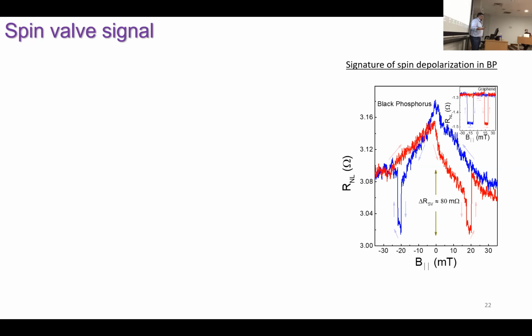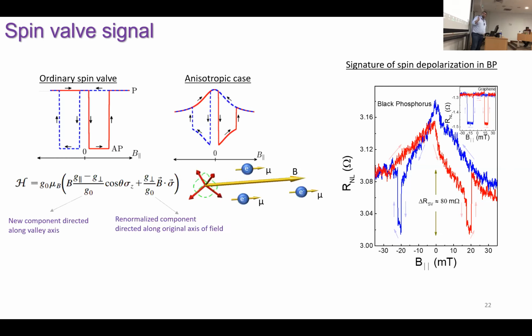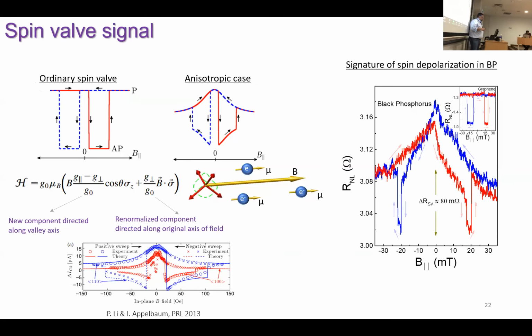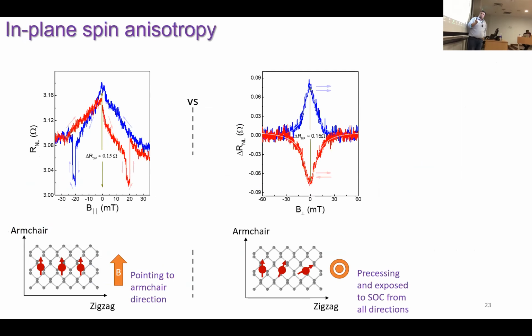Okay, so the question is why the spin lifetime in the out-of-plane direction is very strong, right? It looks like there's an internal magnetic field, which is forcing spins to be stabilized along the out-of-plane direction. To get more information about that, we also did these spin valve measurements. You remember, I was showing you these spin valve measurements a few slides earlier, where you would get this rectangular type spin switching effect. But in the case of the black phosphorus, we do see a very strong spin dephasing effect, which is most likely because of something called g-factor anisotropy in this material. This was also measured in germanium in the past, and it's about the crystal structure, and we are still investigating this effect.